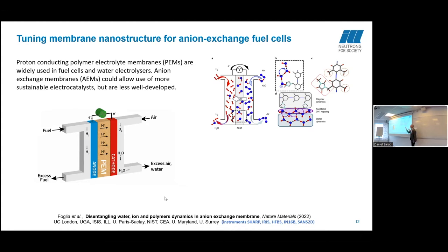The membranes in this case are made from hydrophobic backbones with ionic side chains. So these are hydrophobic backbones with methyl groups, and this is the cationic side chain.